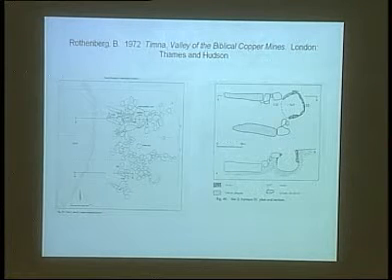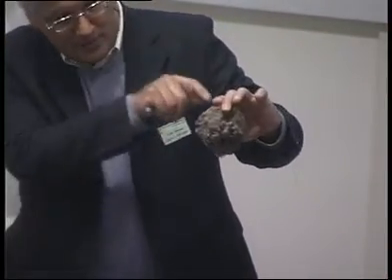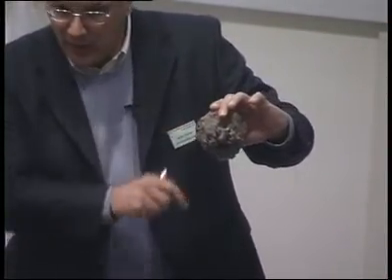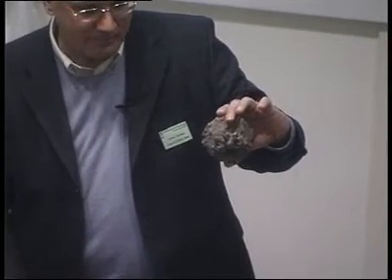Also in the back walls of the furnace are some structures like this. We refer to this as a tuyere. It's basically a hole for the airflow pipe from the bellows to blow air into the furnace, to burn the charcoal, to reach the temperatures, to melt the slag. And we've got examples like this, and like this. And here's another one from refining. Again, very characteristic. The nozzles can be in different positions. That's an important aspect of the model and the interpretation as well.